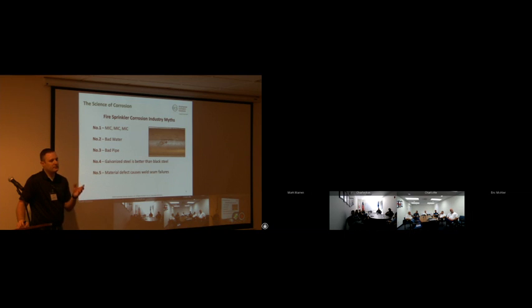It makes that metal look different on a granular level than the surrounding metal. And corrosion does one thing. It looks for differences. Whether it looks for differences in types of metals, and that's where you get into galvanic corrosion, which is when you have two dissimilar metals put together, they'll corrode, or whether it's looking for differences in the granular level of the steel. It's going to look for something that's different, and that's where it's going to preferentially attack.